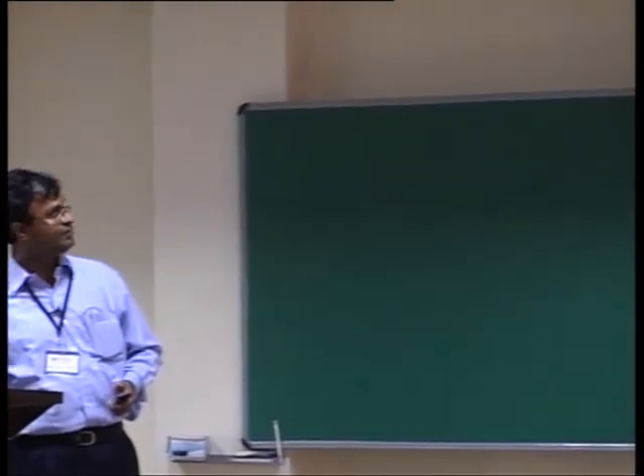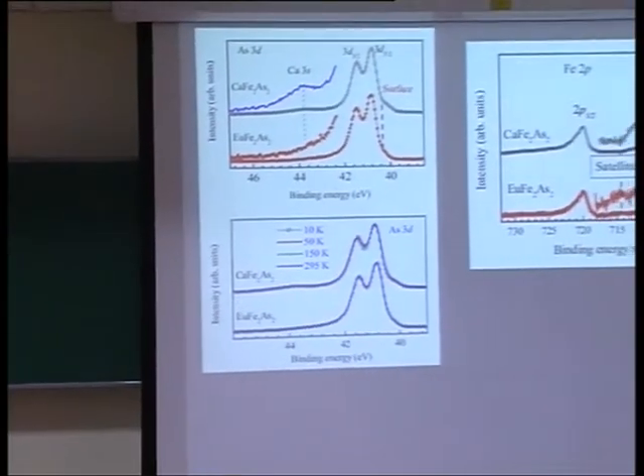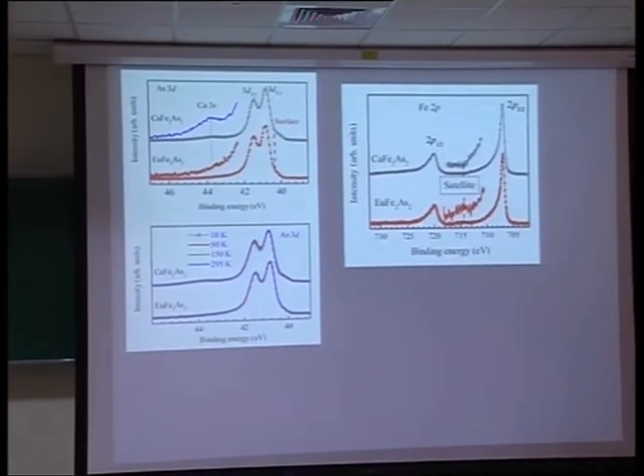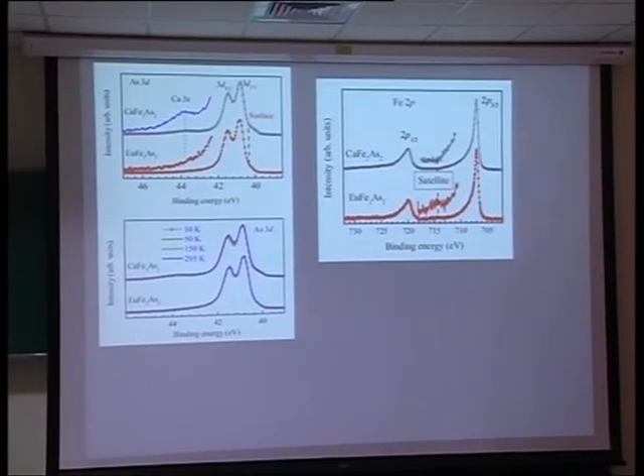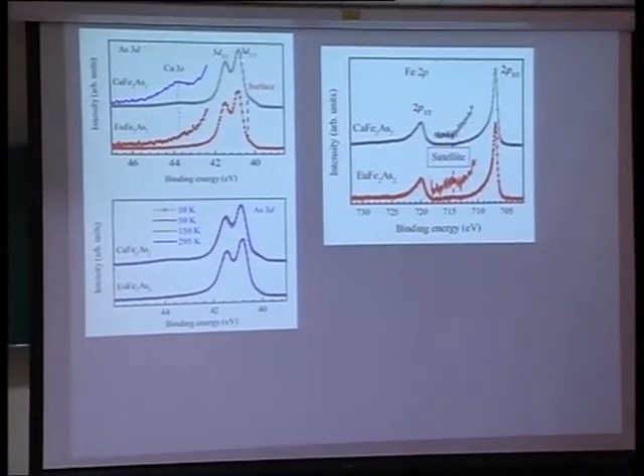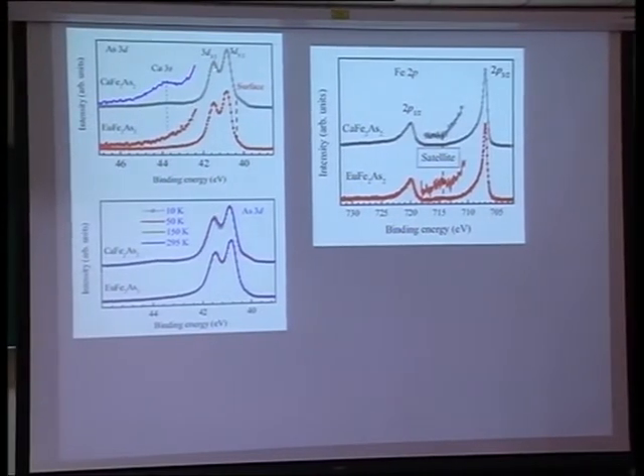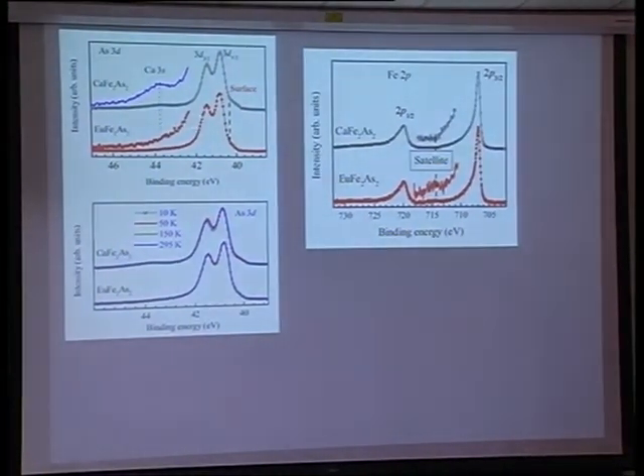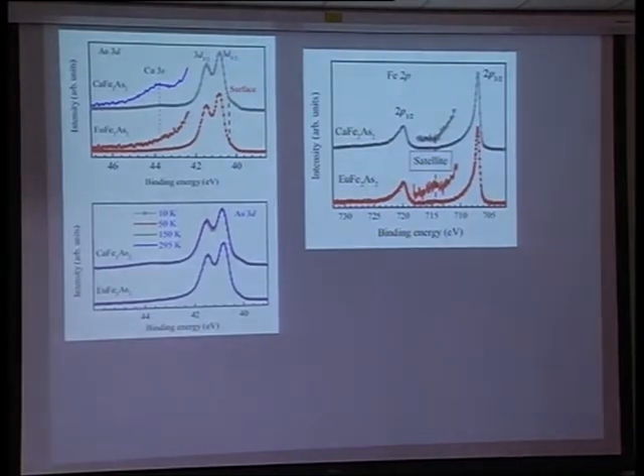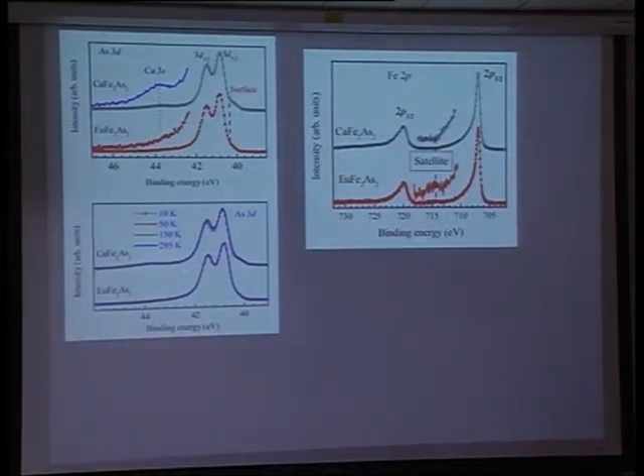So here we have tried to look at various core levels of this material. Okay. So you can see that arsenic 3d shows this two-peak kind of structure due to spin orbit splitting. This is 3d 5/2, 3d 3/2, and they nicely show some asymmetry which is typical of a metal, but they don't show any satellite here. Here also, if you change temperature, you see that they remain almost identical. Now you look at the iron 2p spectrum.